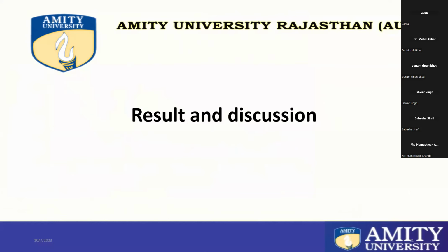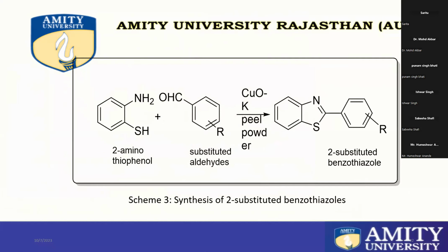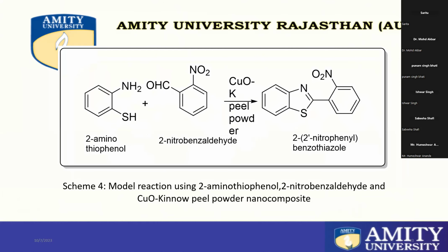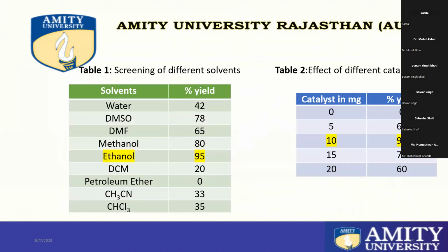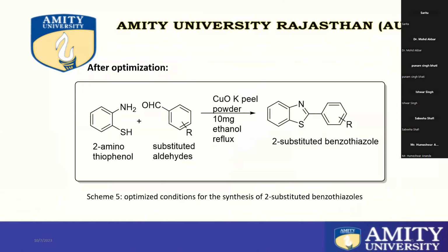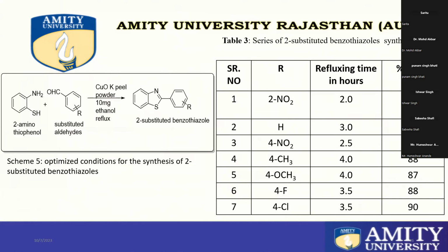Now, result and discussion. I would like to extend the application of the catalyst prepared to 2-substituted benzothiazole. The model reactions or substrates used were 2-aminothiophenol, 2-nitrobenzaldehyde, and the catalyst. So we screened different solvents, and we found that ethanol was giving us the effective conversion at a very high percentage. Similarly, we also tried different catalyst loadings. We found that 10 milligram of the catalyst gave us the effective conversion. And after getting that optimized reaction condition, we tried to extend these parameters to various substituted aldehydes, and we could prepare.